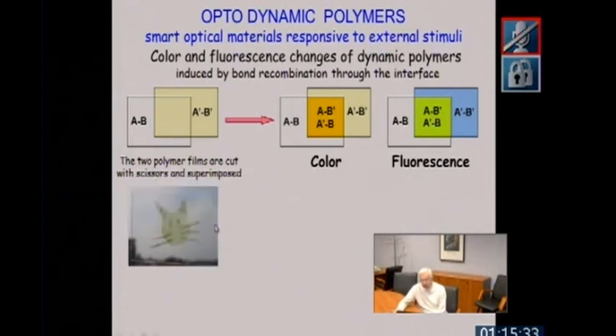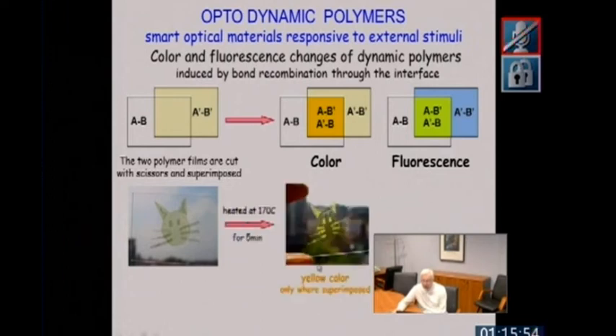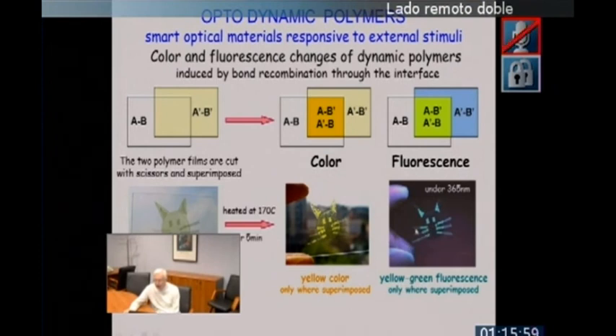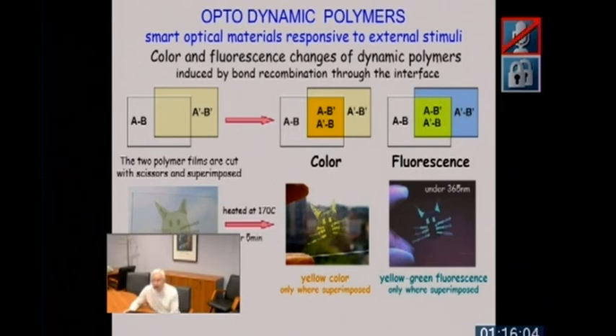So this was done in this way by Japanese co-workers. You have a nice cat here, which has the head and the ears. That is the polymer AB. You have the mustache here, the eyes, and the inside of the ears. That's polymer A prime, B prime. You see that they are superimposed here. So now you heat and you see color appears and fluorescence appears, only where they are superimposed. This, of course, is something which, first of all, indicates that indeed this recombination works at the interface.